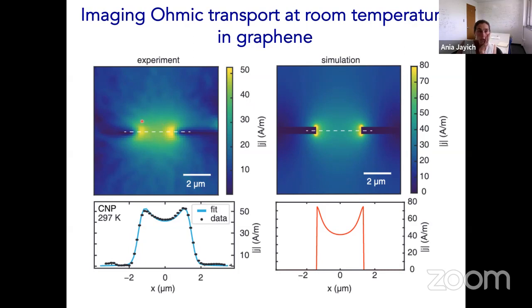Okay, so as I've already shown, if we image the magnetic field through this device and back out the current flowing through the device, we get this image, and if we take a 1D line cut, we get this profile of the current going through the device. The black is the data, and the fit is actually a free parameter model where all we've put in is the geometry of the device. And one can see that we have very nicely imaged the presence of the ohmic profile at room temperature, as one would expect in a graphene device.